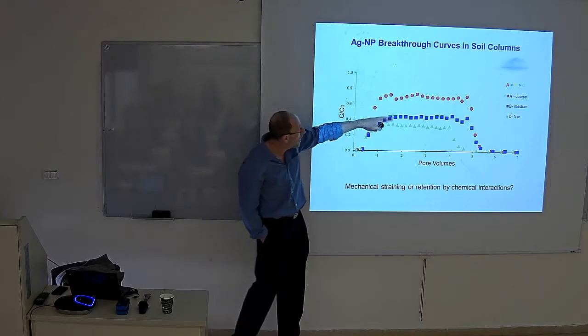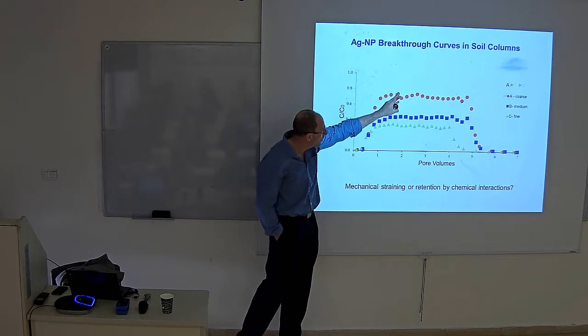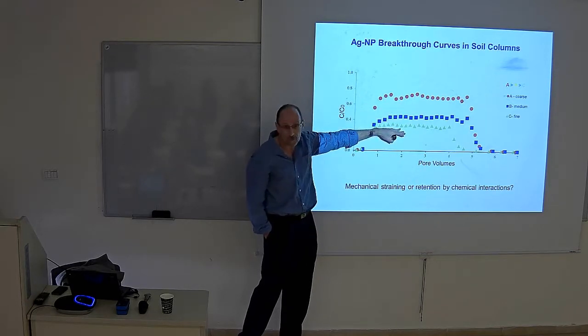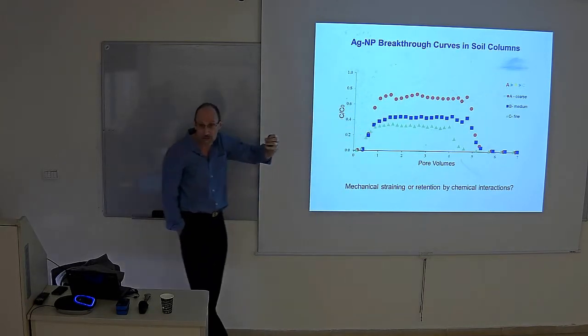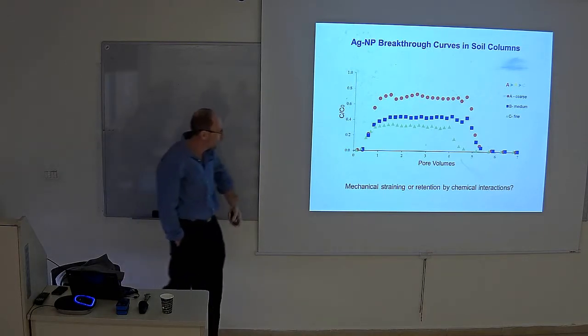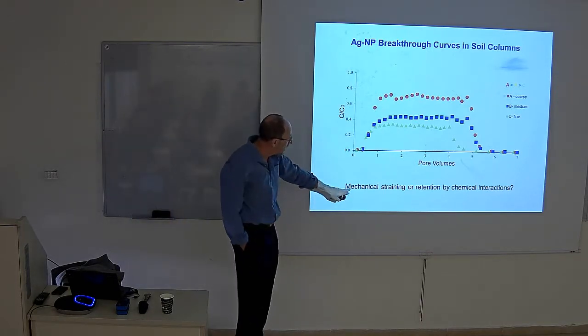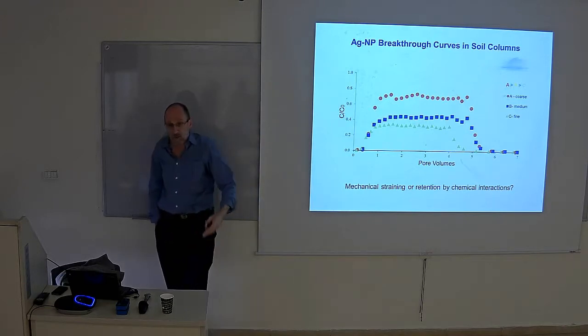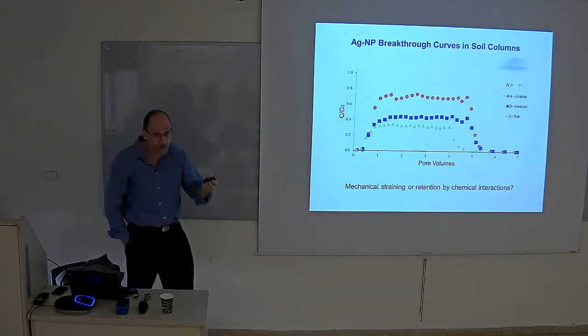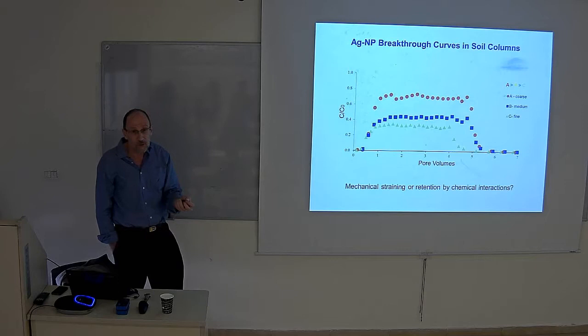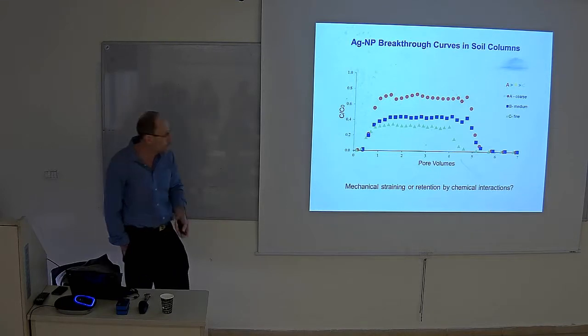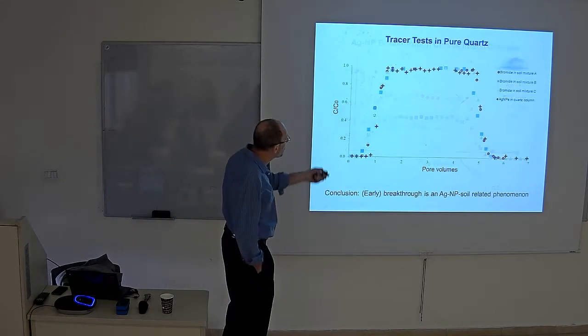Okay, so you can see, and as you would expect, for the coarse, more material goes through. As you go to finer and finer sand, you get more trapping of the nanoparticles. Okay, that makes perfect sense. That wasn't a surprise. Then the question is, is that mechanical straining? Is it retention of some kind? What are the surface effects again? And trying to deal with natural soil with nanoparticles, it's a nightmare. I mean, try to figure out the chemistry on that. So that was the first effect.